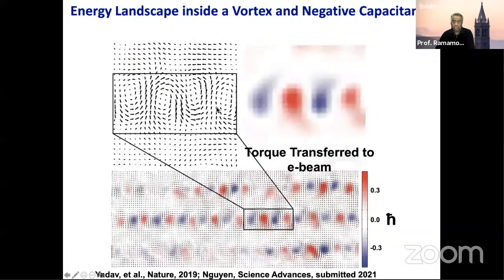Now, when we started looking at these vortices, one of my colleagues at Cornell, David Muller, bar none one of the best microscopists I've seen, has an angstrom electron beam. It's a very coherent electron beam. When you shine it through these vortices, the beam will start to rotate. And you can actually change the angular momentum of the electron. And you can map it out as a function of spatial location. For example, the blue is rotating to the left, and the red is rotating to the right. And this length scale is 5 nanometers, about 12 to 14 unit cells of the material.